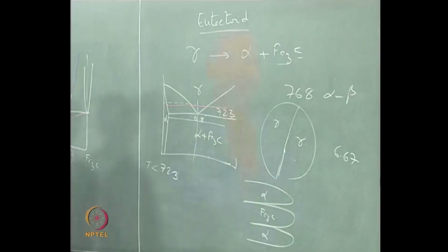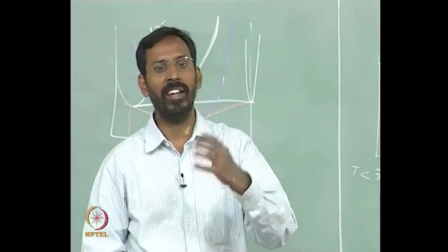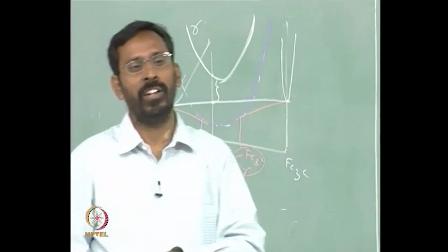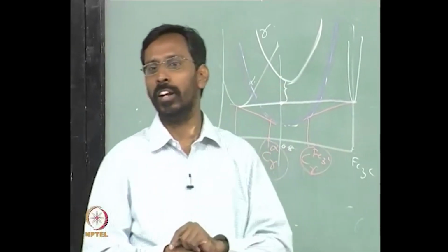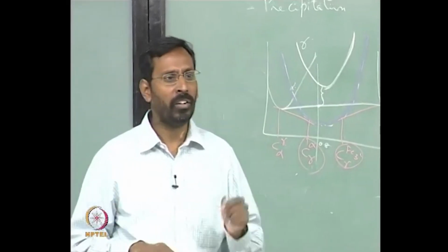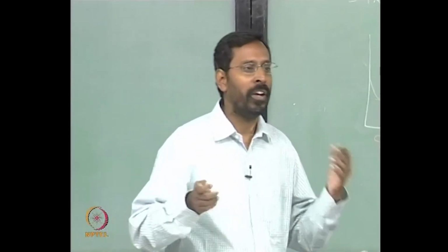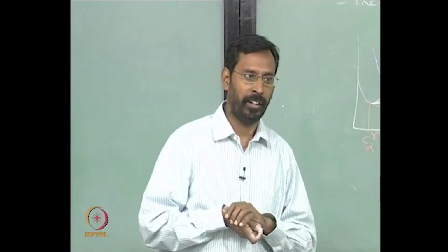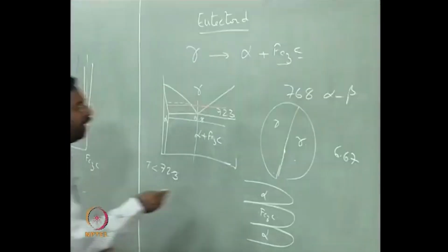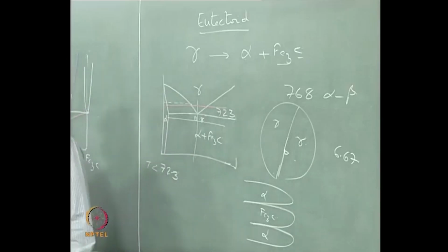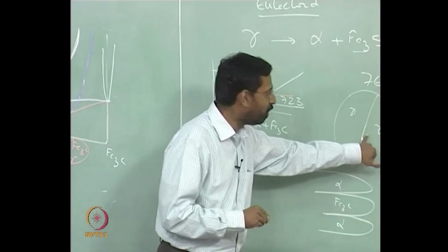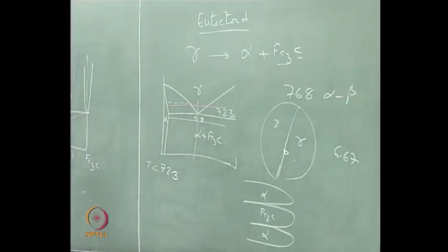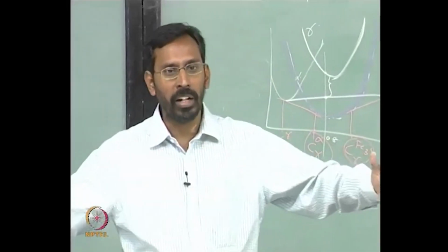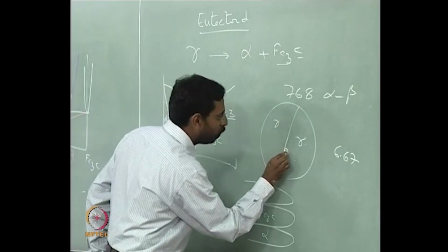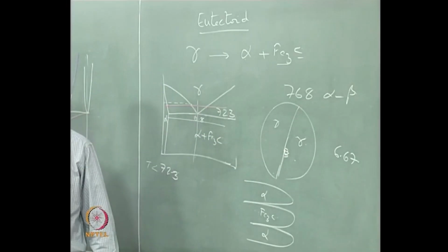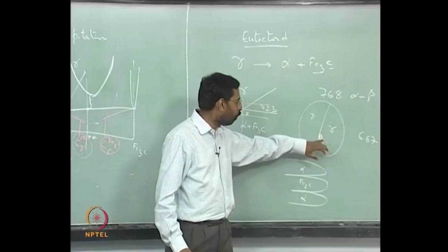So, that means in a small region, if 25% of that particular region has carbon atoms, immediately that region gets converted to Fe3C, and it does not have any problem of nucleation, because it is nucleating at the grain boundary, it is not nucleating within the grain. So, there is no major surface energy problem or strain energy problem for it, because the nucleation is at the grain boundary. So, happily a cementite will nucleate, and the moment cementite nucleates, obviously the regions adjacent to that get depleted in carbon, because carbon has come closer to a particular place from both the regions, and as a result this particular region next to it becomes ferrite, and for becoming ferrite it also rejects out carbon in both the directions.